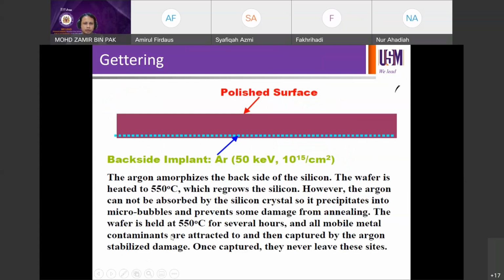Okay, the polished surface versus the rear side. So the gettering, this is another way to do it. The argon amorphizes the backside of the silicon. The wafer is heated to 550°C, which regrows the silicon. However, the argon cannot be absorbed by the silicon crystal, so it precipitates into microbubbles and prevents some damage from annealing, right? This is another way to do it.